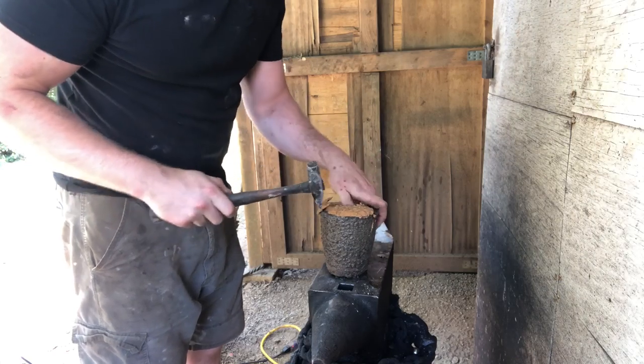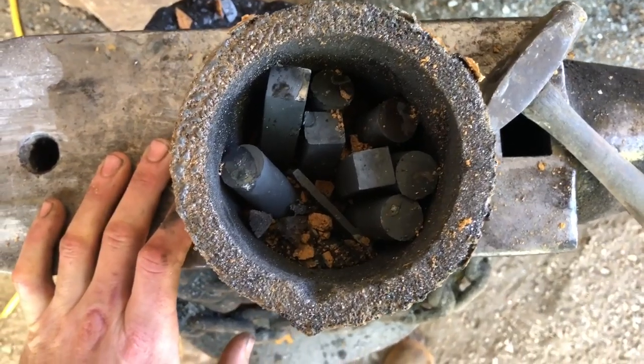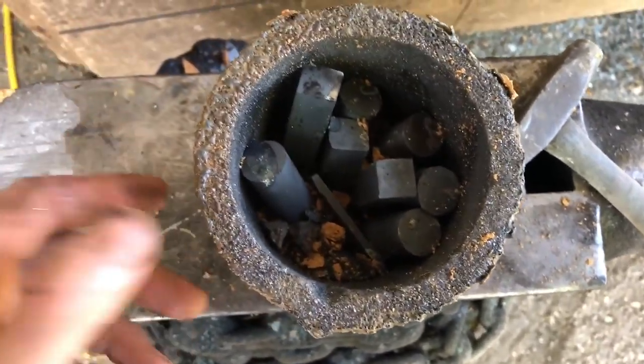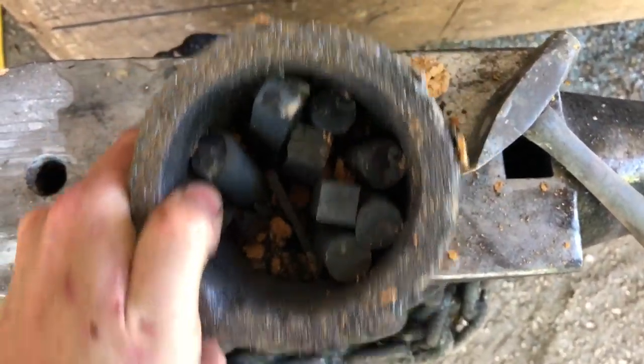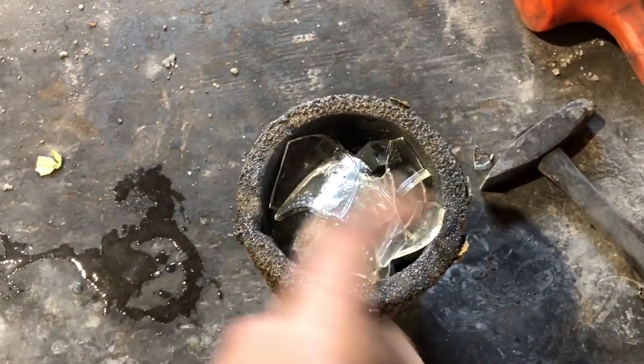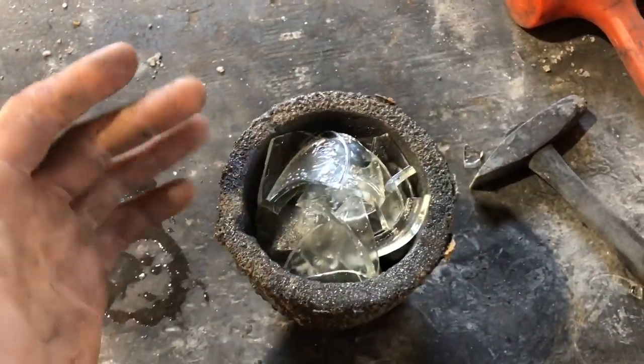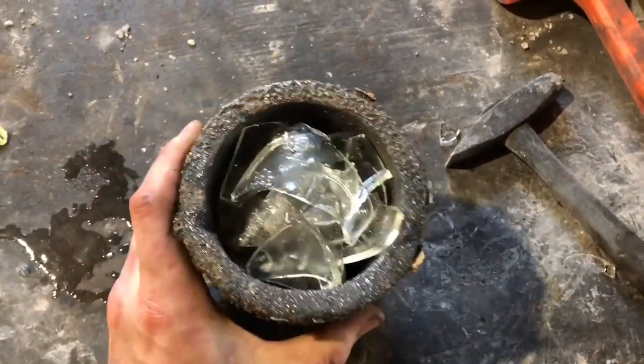This is pretty cool — I feel like a kid at Christmas. Well, this is definitely not what I wanted to see. There are still pieces in there; it looks like it only started to melt. Maybe we didn't cook it long enough. So I'm going to take a chance and throw this thing back in the furnace and see what we can come up with. I threw a bunch more glass in — ideally the glass should melt before the charcoal powder gets hot enough to burn, keeping everything sealed and letting me see when everything is liquid.